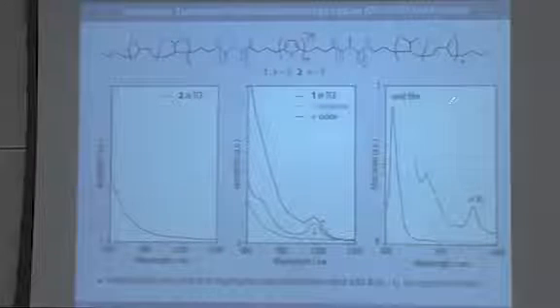So if we take our original solution, we add a reductant, we can quench them. If we add an oxidant, we can reestablish them. And we also observe the same bands in solid films of our material that have been carefully kept under argon.